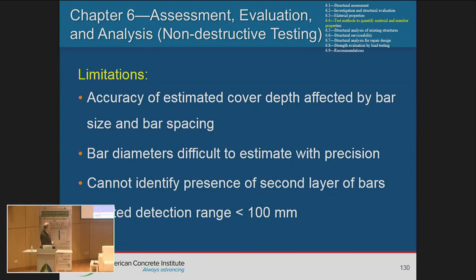The limitations, again: if your bars are at a depth greater than 100 millimeter, or if you have multiple layers of bars, it cannot identify that. And also, if you have a lot of bars, then determining the size and spacing of the bars may be difficult.